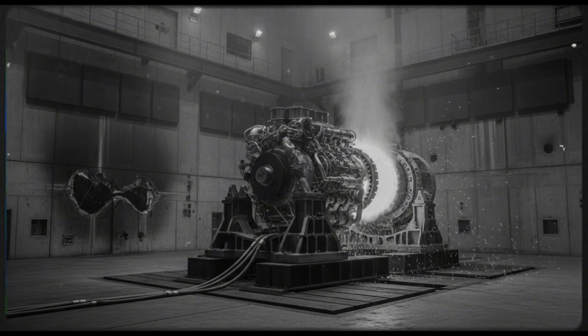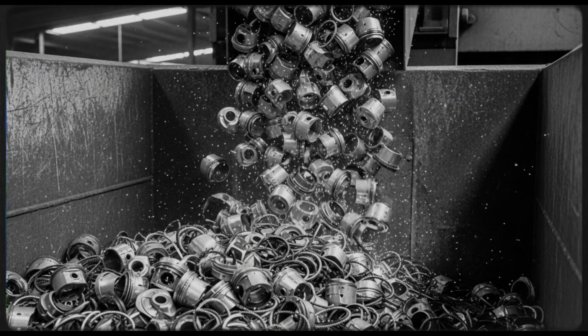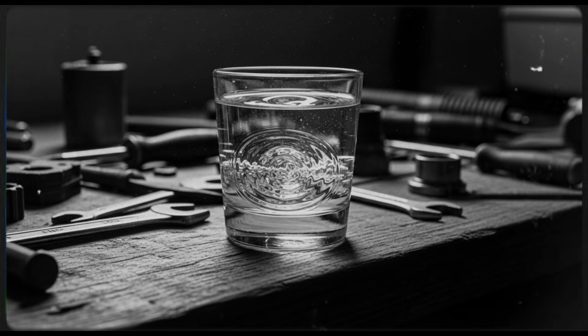Cars were painted in drab matte colors because chrome for bumpers and trim was unavailable. Then there was the ever-present issue of quality control. When you are plating 500,000 rings every month, errors are inevitable. A poorly mixed batch of plating solution, a sudden power fluctuation, a contaminated rinse tank, any of these could result in rings with a weak chrome bond. The rings would look perfect and pass a visual inspection, but under the stress of combat, they would fail. And when a ring failed at 20,000 feet, people died.